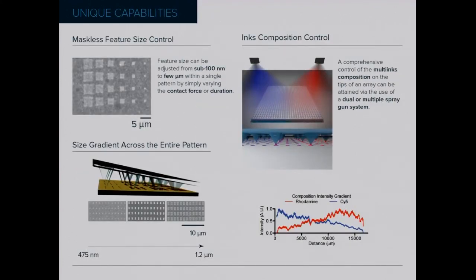But you can begin to play tricks with this. And this is what we didn't anticipate when National Geographic kind of picked it as this really important thing. We could take the array and we could intentionally misalign it. And when you do that, look what happens. This side of the array hits first, this side hits last, and we have an intermediate state in between. Well, that compresses the tips. So what that leads to is a gradient of features where they systematically change in size from small to large.